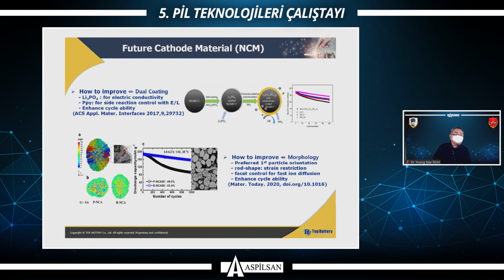The dual coating is one of the best solutions to protect the surface of high nickel cathode material from electrolyte decomposition. In this dual coating process, Li3PO4 is effective for electric conductivity enhancement. Polypyrrole protects against side reactions with the electrolyte. It leads to enhanced cyclability.